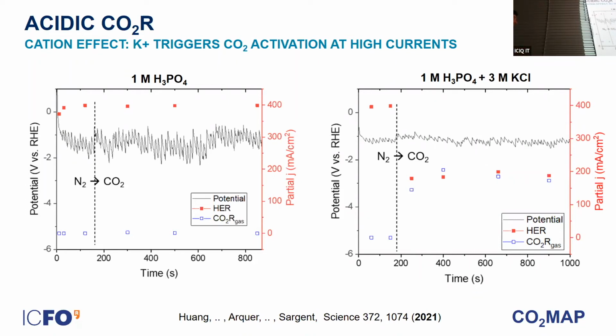So, okay, we thought, based on the literature too, that recently many groups have been studying the role of cations in this CO2 reaction. So we thought, okay, let's play with the cations in the system. In this case, we have the bare 1 molar phosphate buffer electrolyte with around pH 1. You see that when we change the stream from nitrogen to CO2, so we start providing CO2 at this point, for a fixed current density, nothing happens. So we don't have CO2 reduction.